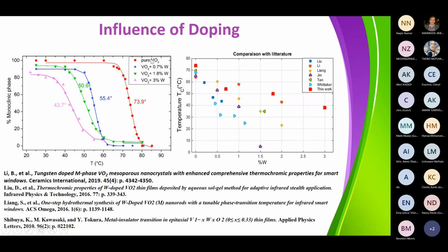We went from pure VO2 to 3% of tungsten, and you can see that when you increase the concentration of tungsten, you decrease the transition temperature. In this case, we were able to decrease it by something like 30 degrees Celsius. And so now we are very close to room temperature. So it means that the tungsten is quite efficient to reduce the transition temperature.